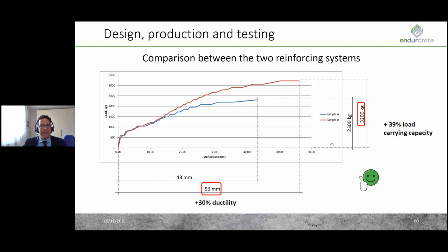If we look at the load deflection curves for a comparison of the mechanical performances, we can see that the TRC solution provided enhanced ductility, about plus 30%, and also enhanced the load carrying capacity with plus nearly 40% with respect to the traditional, let's say the benchmark solution.